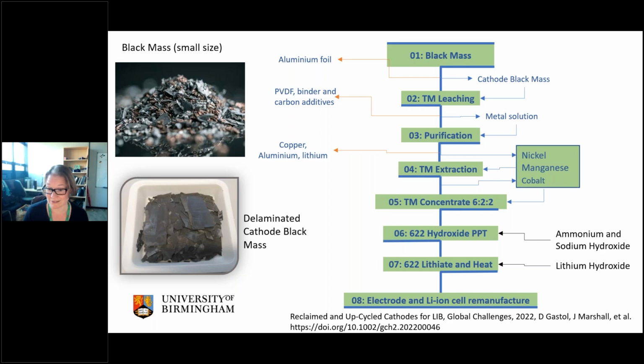Because the old technologies, such as the Nissan Leaf, which was originally a mixed cathode of the spinel and an NCA, isn't used really very much anymore. And more typically, high nickel-based materials are used instead. NMC 622, NMC 811. So we can change the concentration of these transition metals. We can then reprecipitate the hydroxides, lithiate, and remanufacture or upscale the cathode material.